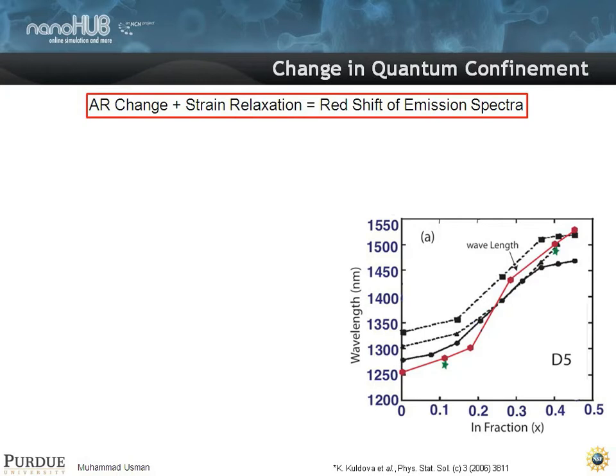We prove that by, instead of having indium gallium arsenide around as a buffer, taking indium aluminum arsenide, which has a much larger band gap but roughly the same strain behavior. And we basically get the same points that we had computed before. So we get the same results. These are the green stars here.